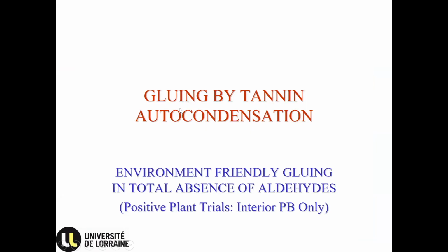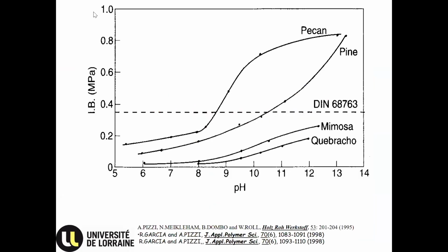Now, going back to autocondensation, the Japanese consider this an environment, but it's only interior. They want something that could take moisture content much better. And you can see here the internal bond of boards manufactured with only some silica or silicates, I'm talking about 2%, 3% of this, that give autocondensation, self-condensation of the tannin. That's pecan tannin, that is pine tannin, that mimosa and quebracho. In the case of mimosa and quebracho, a high amount is needed just to pass the DIN standard that is now the European standard.